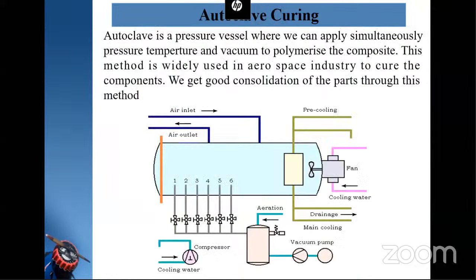Here is an equipment called the autoclave for curing. An autoclave is a pressure vessel where we can apply pressure, temperature and vacuum simultaneously to polymerize the composites. This method is widely used in the aerospace industry to cure components. We get good consolidation of the parts through this method. Here you can see this is a pressure vessel where we can keep the component inside and simultaneously apply heat and pressure through air, and vacuum also, in order to extract the volatiles from the component. This is an important equipment in the aerospace industry.